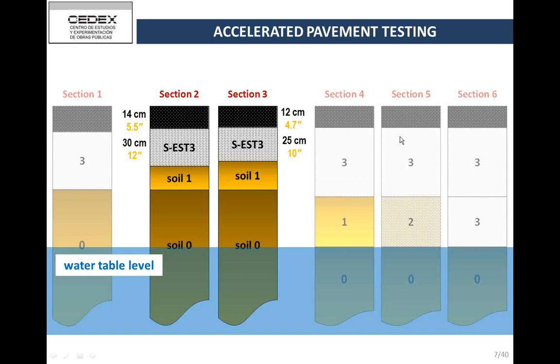Well, what we found in Mozambique, also going to higher strengths, is that the performance is different, because you might have a very hard surface and less crumbling, and for that matter we prefer that. But then you must be very careful, because if the layer is very small particles, then you can have slippage because of the hard surface, and losing the bond in a different manner.